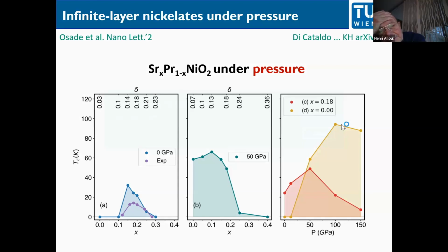Yeah. So the variation of the square lattice parameters are much smaller in the nickelates. So most of, so far at least, everything is grown on STO or very, very similar substrates. And then in cuprates, you have a much larger variation of the hopping parameters because you have bulk systems. And then if you have different numbers of films, you change the system, the in-plane hopping also quite substantially.